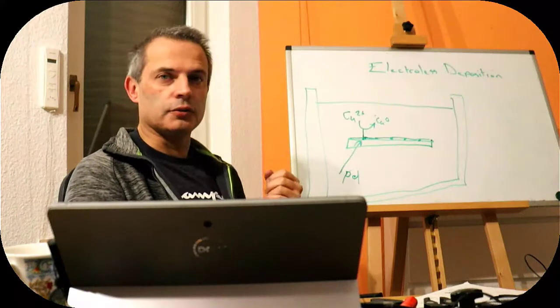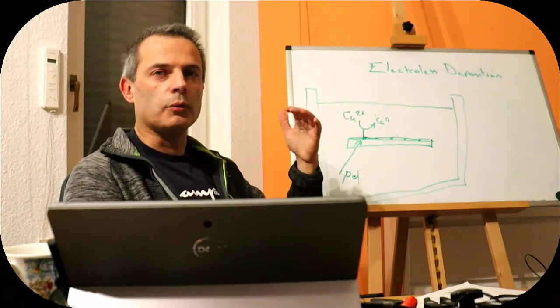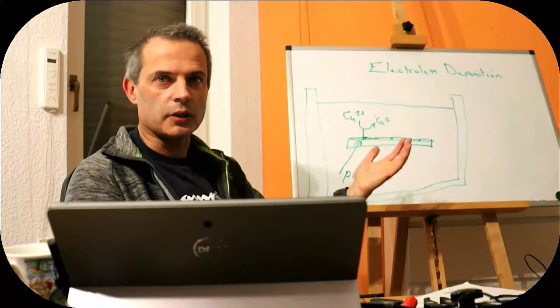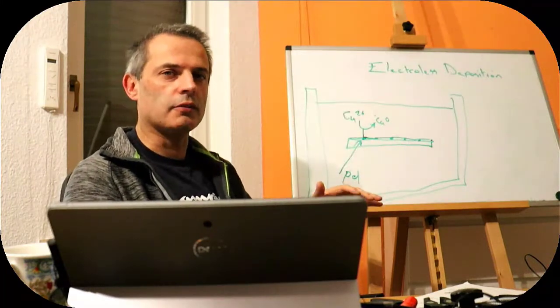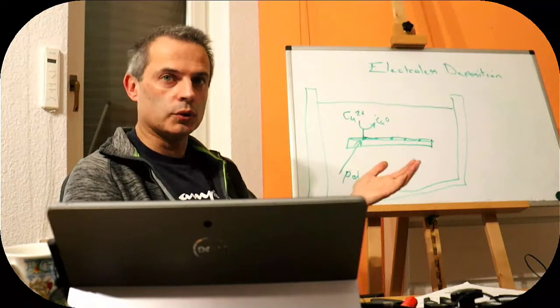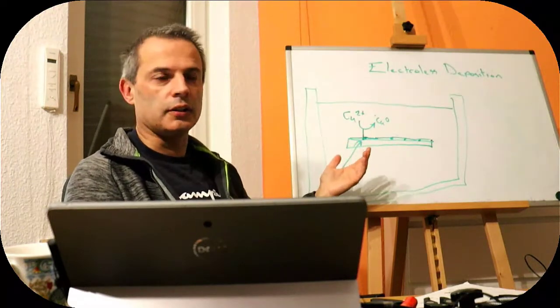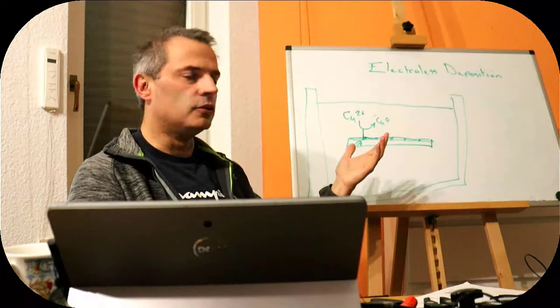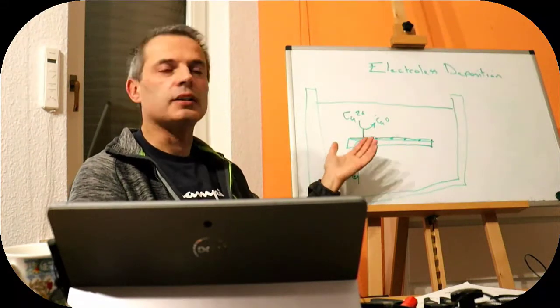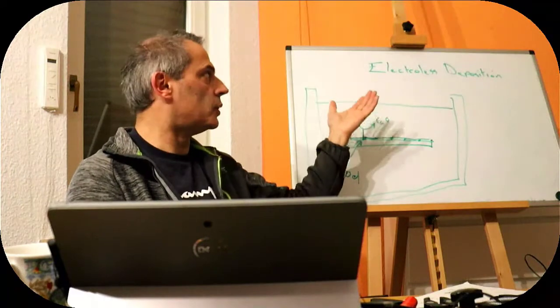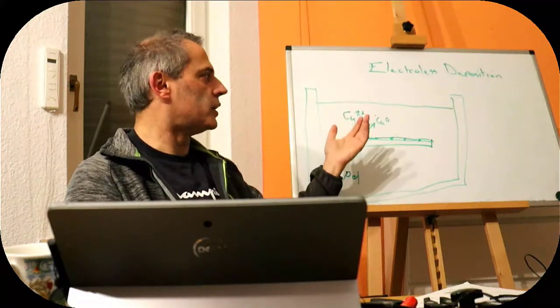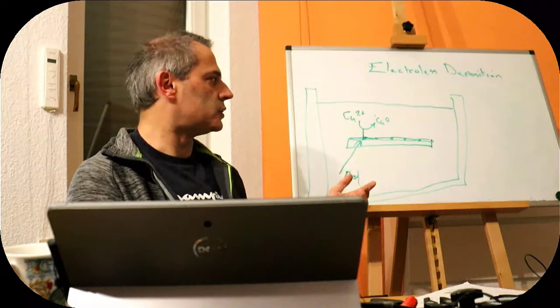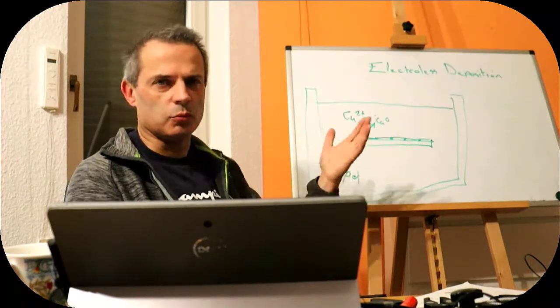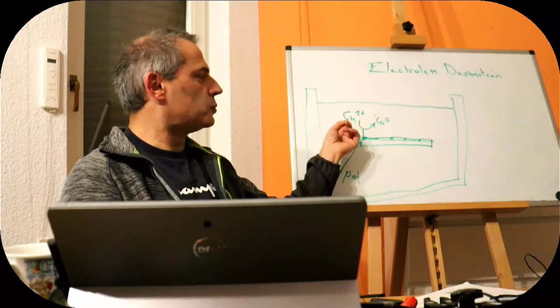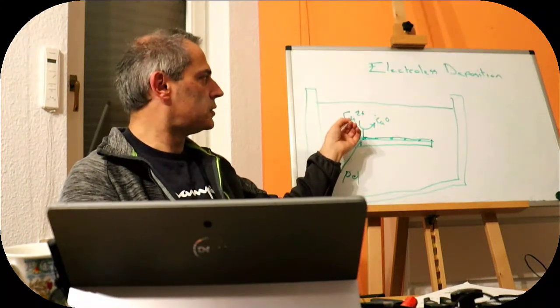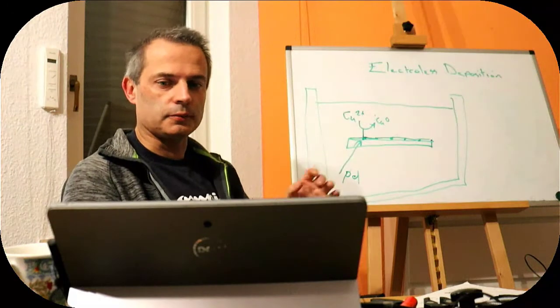Typically, oxygen from the air will be an issue, but from our Pourbaix diagram, we will not get to a low enough reducing potential to reduce the water, because the reducing agent is never going to be that strong. We will fail to do electroless deposition in water with any of the metals that have a lower reducing potential than water, because everything won't work, because we need to get so close to this just depositing condition.